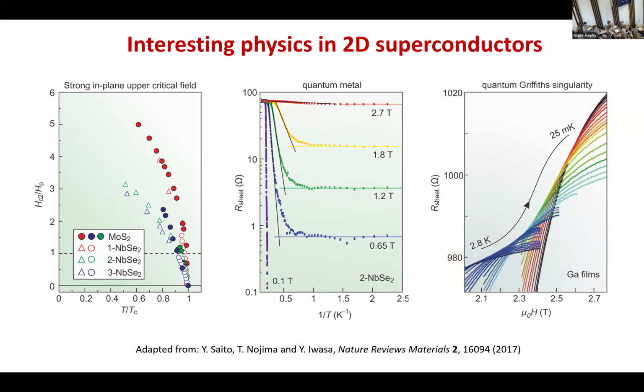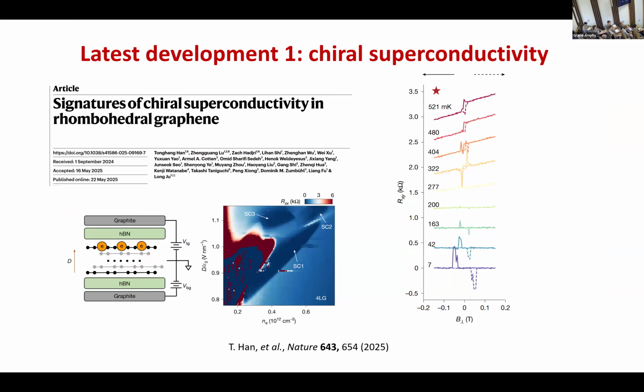So the basic idea is that there is a transition from superconductivity to some normal state. However, this transition is not a single point transition. If you see that for different temperatures, if you sweep the B field, the crossing points of these curves move toward higher magnetic field when you cool to a lower temperature. So this is a basic feature. People call this quantum Griffiths singularity. Why I'm not talking about this is because now people also find this in 3D superconductors. So this is not just limited to 2D, probably because 2D is just easier for tuning.